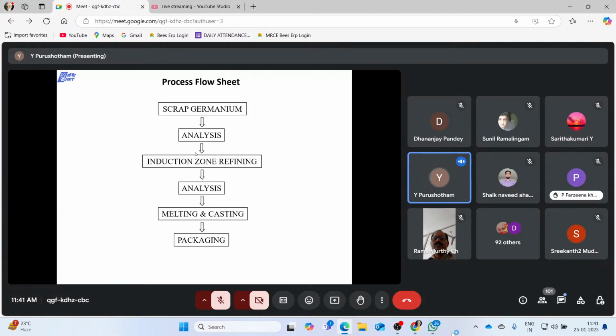They told us to submit a project, so I submitted one. This is the process flow chart: we take contaminated germanium available at their laboratory, which has been analyzed. Germanium's melting point is 950 degrees centigrade, so this cannot be done by resistive heating. The conventional resistive heating that I have shown till now, whether for tellurium, cadmium, or zinc, involved melting points below 500 degrees centigrade. But germanium is 950 degrees centigrade, and resistive heating may not be effective.